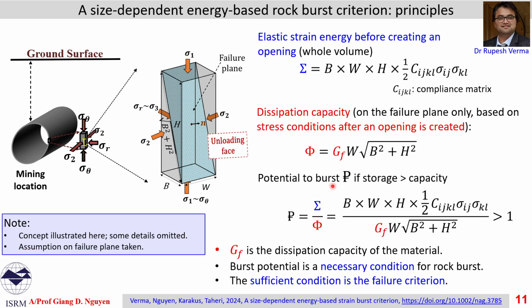So rock burst in this case happens if the specimen stores energy more than the capacity to consume it. That's the ratio, and that allows us to give an indication or even magnitudes of rock burst. So if storage is greater than capacity, rock burst can happen, but this is not always the case, because it still depends on another sufficient condition, which is the failure criteria.